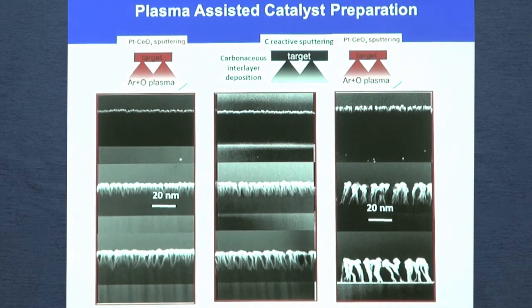This is an example of how it works. We coated a silicon wafer, which is also very flat, with a thin film of carbon, which is amorphous. After some time of etching, we etch these kinds of holes. On the other hand, if we use another type of carbon, for example carbon doped with nitrogen, you can see that the etching is much more efficient, and instead of creating holes, we can go until some kind of nanonoodles which are coated with the catalyst.